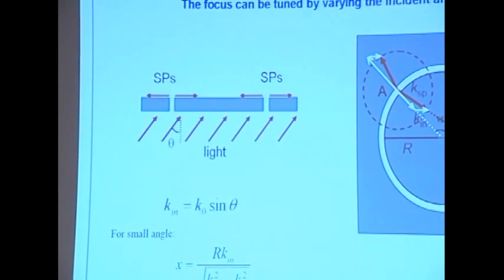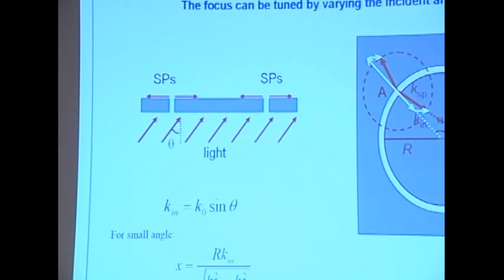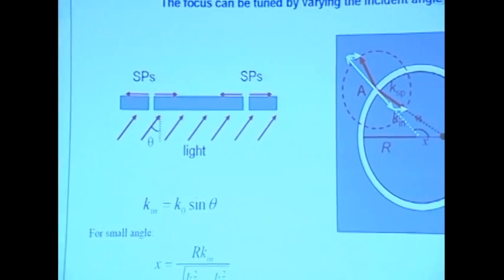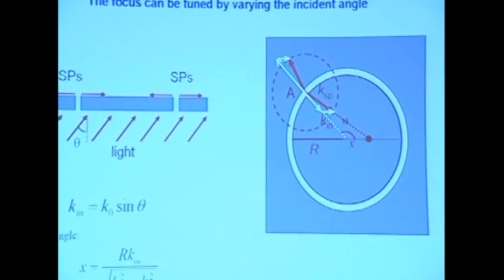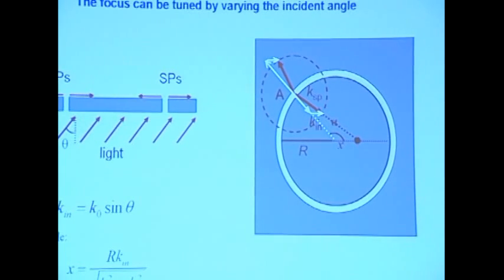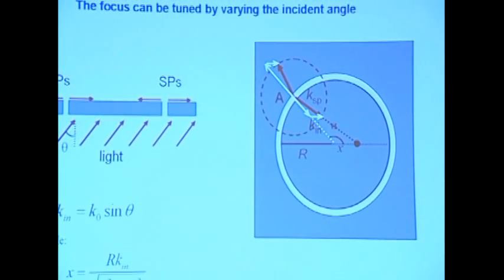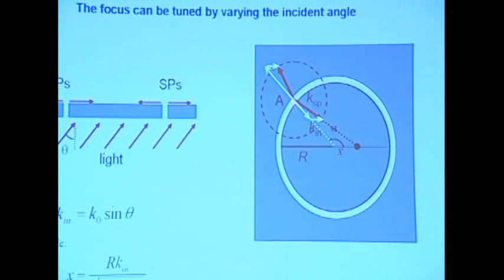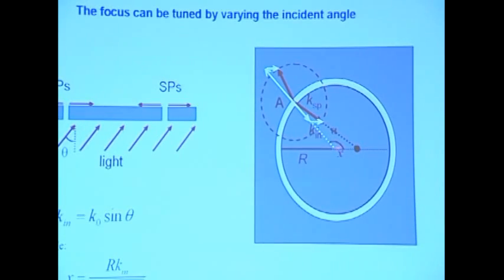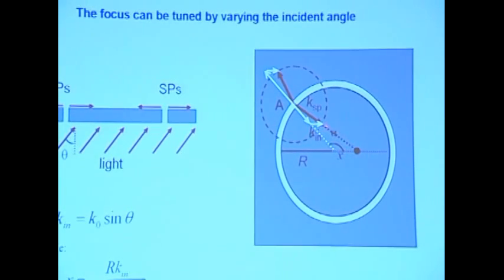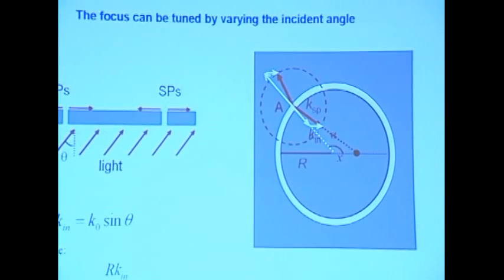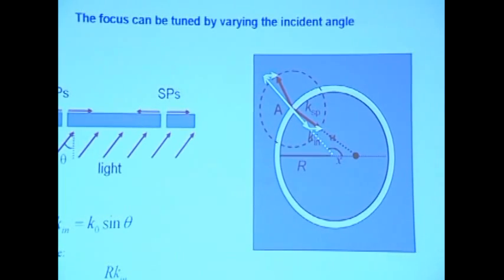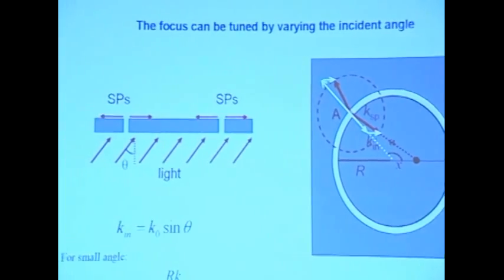Essentially, you give an extra photon momentum to these surface waves. However, the magnitude doesn't change because that's dictated by the dispersion curve. But it's just like riding a bicycle. There is a basketball hitting the rider on the side, and you make a turn. So essentially, this turn moves what was originally focused at the center off the center. Basically, it's the little bit of extra photon plasmon momentum you provided from this angular incidence.